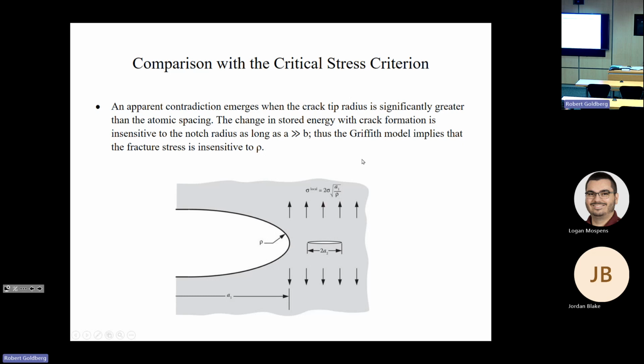Now, we're going to be doing a couple things with this picture, but for right now, the thing to note is that a contradiction emerges when the crack tip radius is significantly greater than the atomic spacing. This is obviously blown up a lot for exaggeration, but you can see here that our radius of curvature is not infinite. There is a radius of curvature, and this radius is significantly greater than the atomic spacing. And so the change in stored energy with the crack tip formation is insensitive to the notch radius as long as the length of the crack is significantly greater than the thickness.